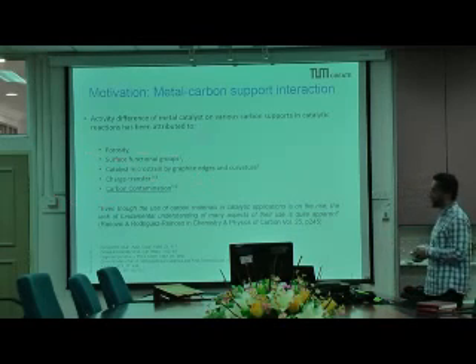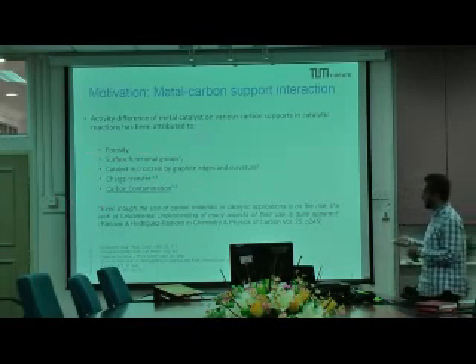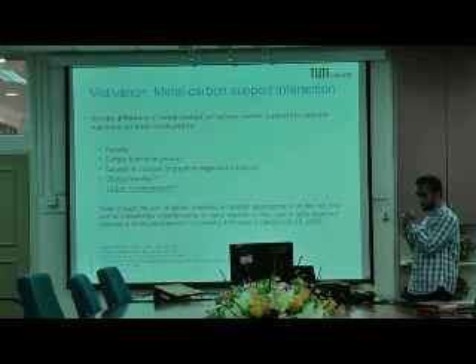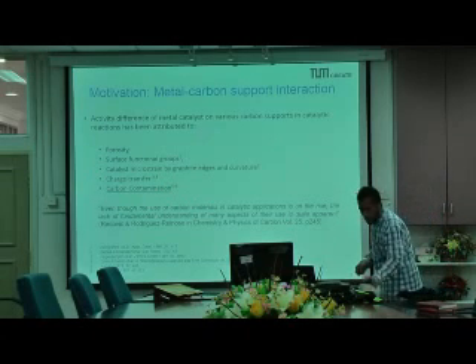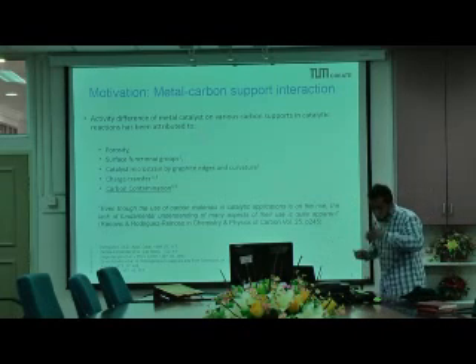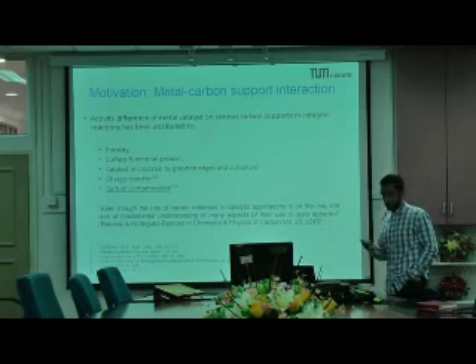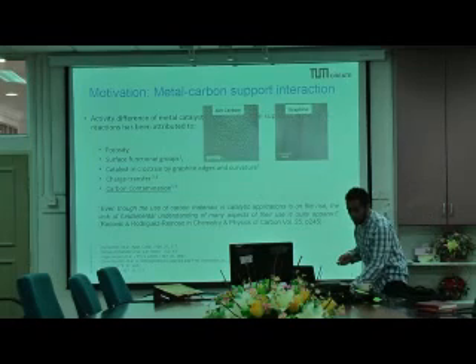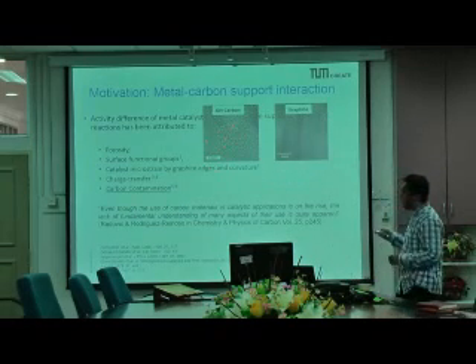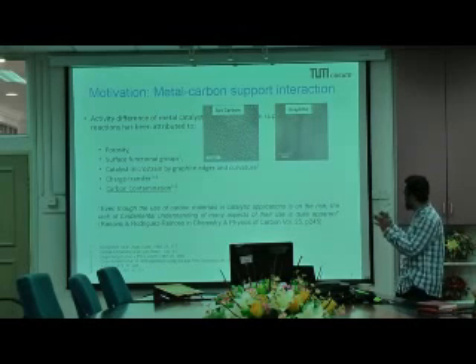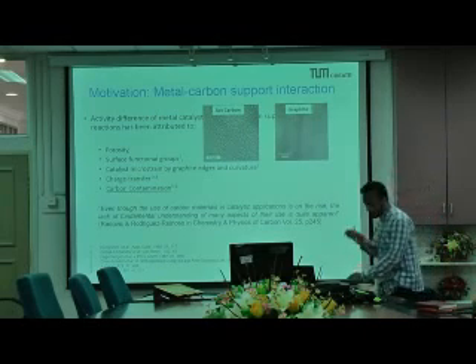So in the literature, people have attributed these differences to porosity, surface functional groups, microstrains, and carbon contamination. And I chose to focus on the easiest one to investigate: what is the role of the metal, what is happening on a metal when it's sitting on a carbon support. We can discuss it later. These other types of variations are quite difficult to control in the carbon material. Right, so going back to the motivation again, active carbon is an amorphous structure, graphite is a very crystalline, regular material.